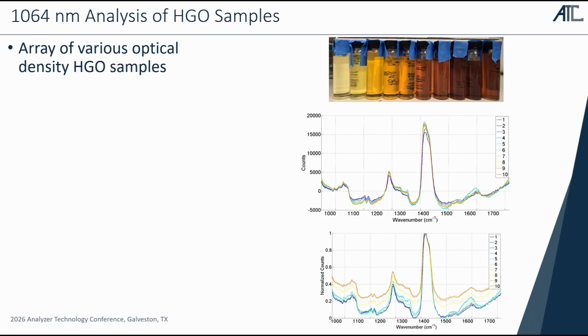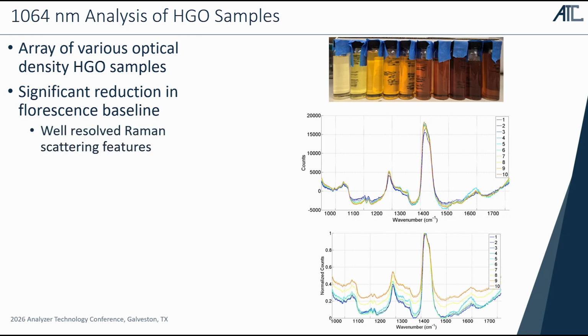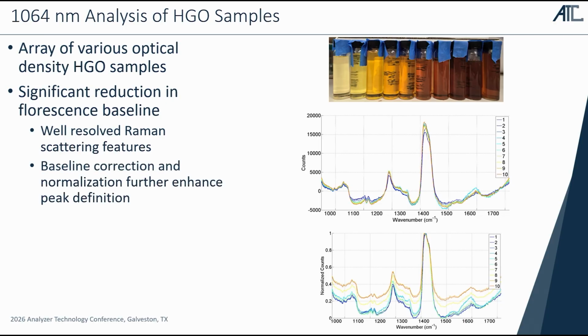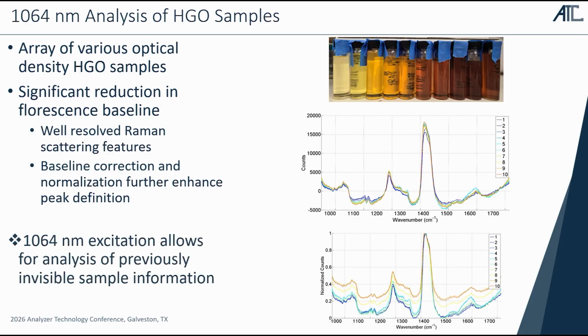And then you can see that upon analysis of the same sample set with 1064 nanometer Raman, you can see that the property that I was mentioning before really rings true. You can see there's a significant reduction in the fluorescence baseline, as well as new Raman features that are becoming visible, and not only visible, but also highly resolved. And then upon further baseline correction and normalization, we can further enhance this peak definition. And so this really demonstrates that the 1064 nanometer excitation is a really unique workaround and allows you to access samples that were previously inaccessible with the 785 nanometer configuration.